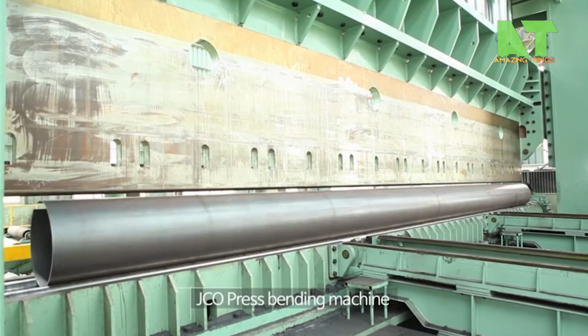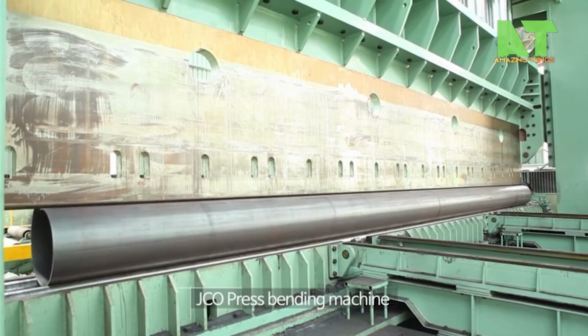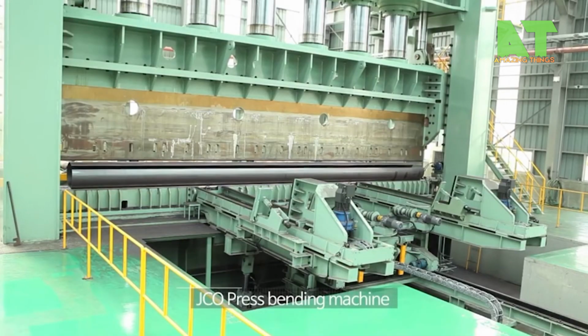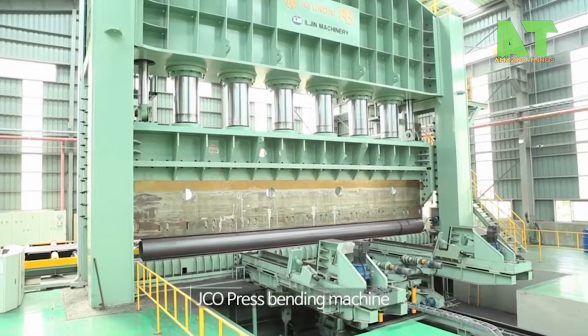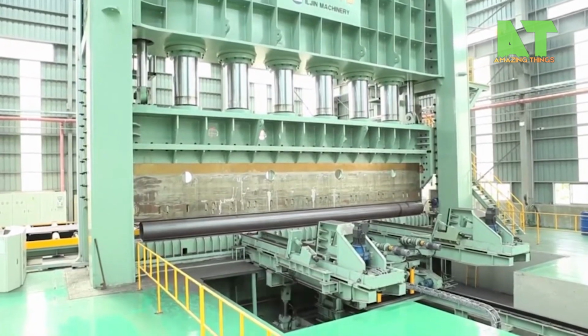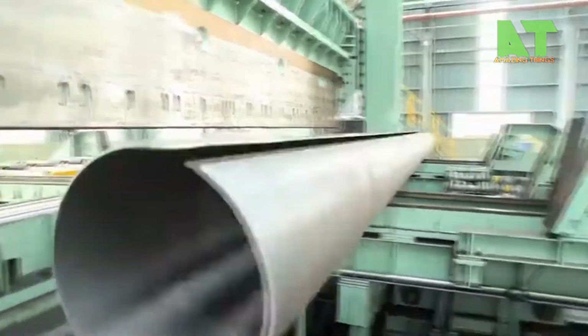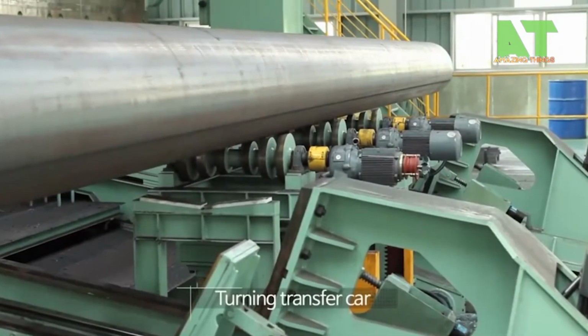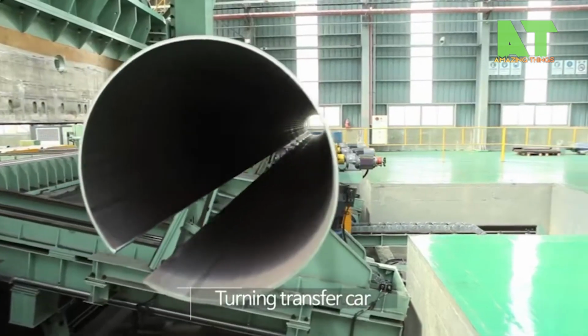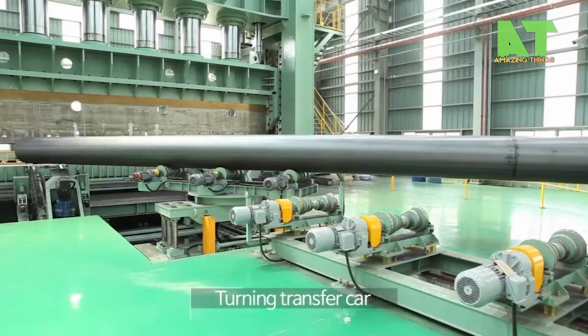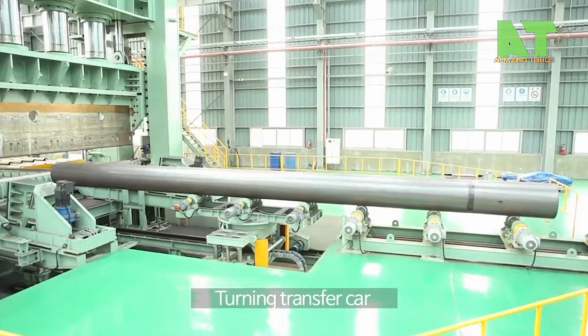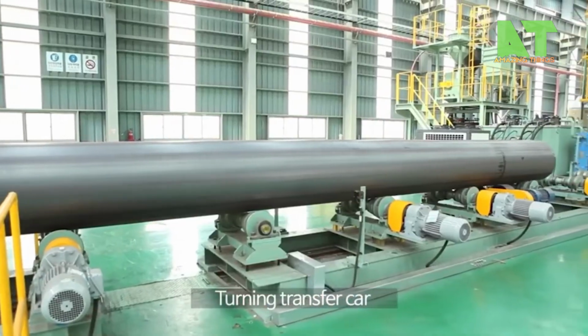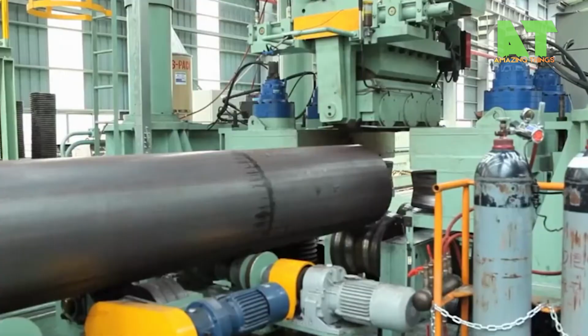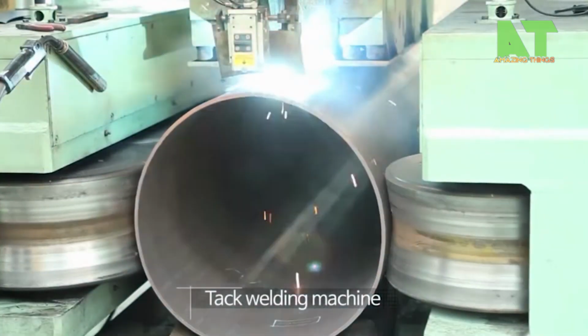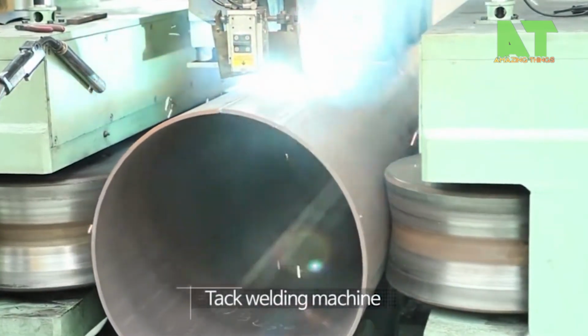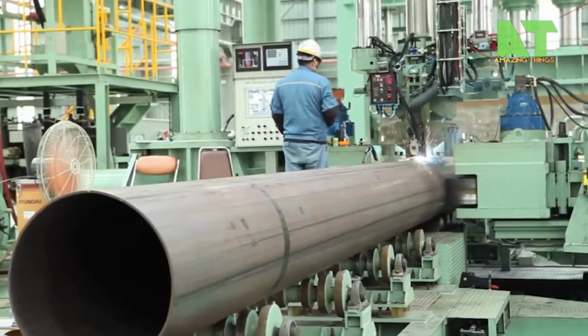Next comes the critical welding stage. The preformed pipe shell is first tack welded along the seam to hold its shape, then moved to the internal submerged arc welding station, where the inside seam is welded first. A submerged arc process means the welding arc is completely buried under a layer of granular flux. This shields the weld from atmospheric contamination, produces an incredibly clean and strong weld, and virtually eliminates spatter. Then the pipe moves to the external SAW station for the outside pass.